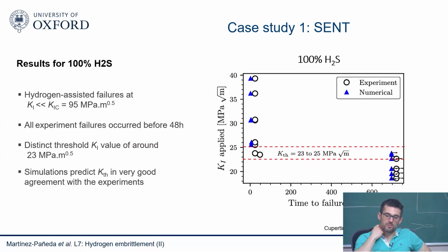I should say, this is what people in the industry are a bit puzzled about. In a way, not puzzled, but worried about. So they have a bit of a scatter here. They do this test, and all the tests fail quite early. In all the experiments, they fail in 48 hours. So some of them will say, why don't we just stop the test after 48 hours? We save a lot of money. We need to do many of these certification tests. This is what some people would like to do.